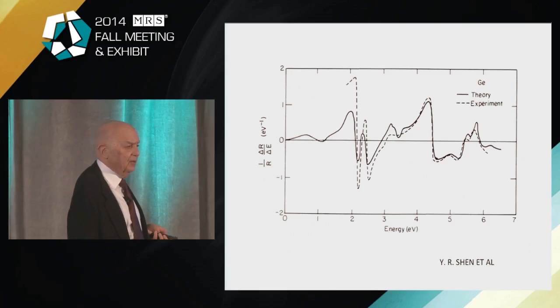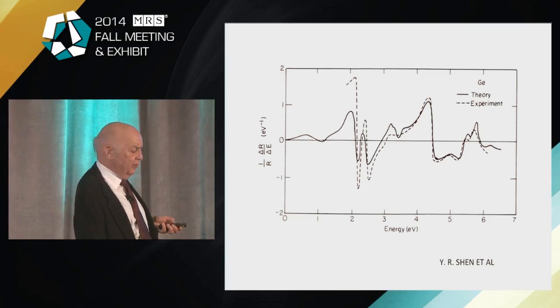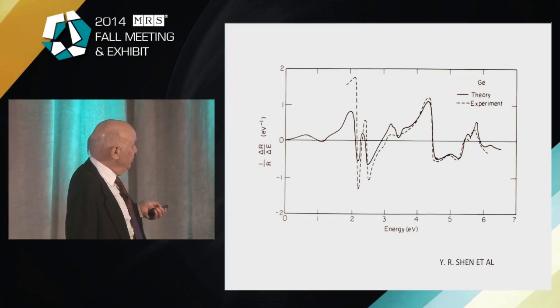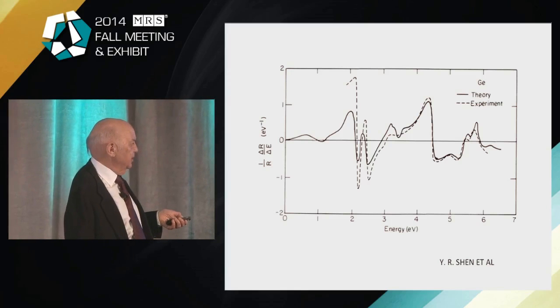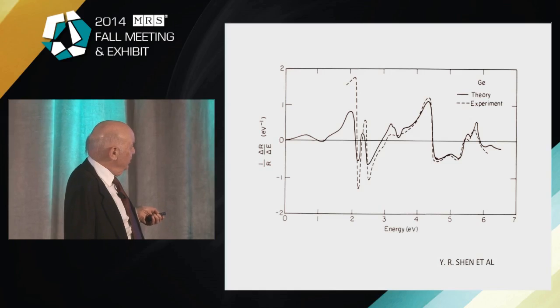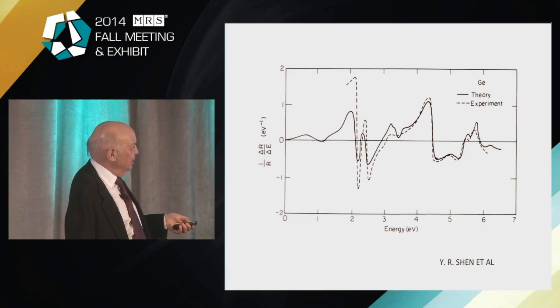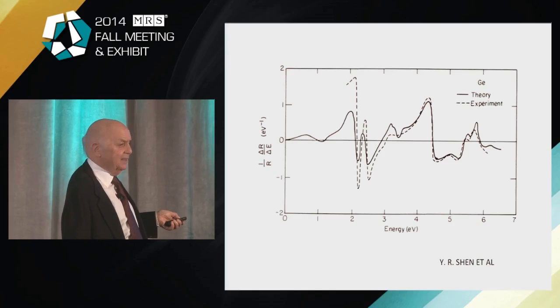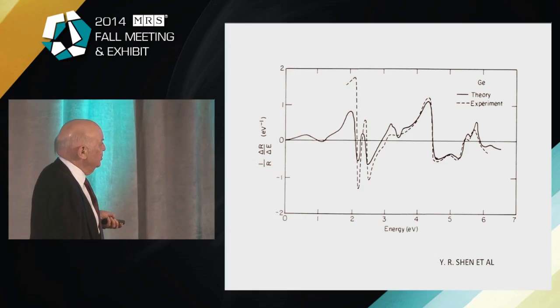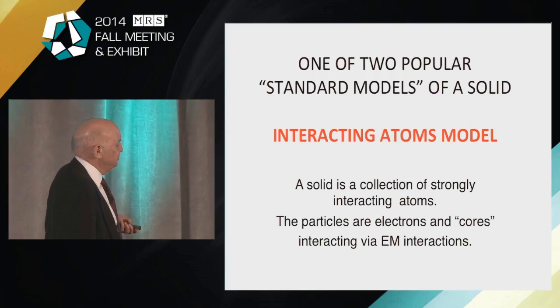And better optical spectra. In fact, the big breakthrough was, instead of just measuring the reflectivity of a solid as a function of energy, one would take a derivative of that reflectivity, and that derivative would show all the detailed electronic structure. And as you see here, theory and experiment are in very good agreement. This discrepancy was explained later as due to so-called exciton effects, and all of this structure was explained using only 3 parameters to determine the electronic structure.